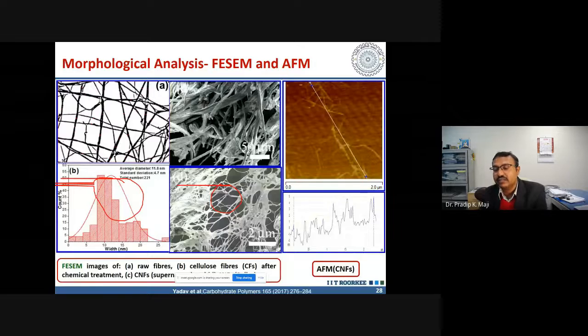Thickness of the material, though it is coming a little less, is still reasonable compared to what we got from FESEM. Here we are getting somewhere 4 to 5 nanometers average thickness, because whatever line we are drawing and whatever it is touching, based on that, it is giving the thickness.